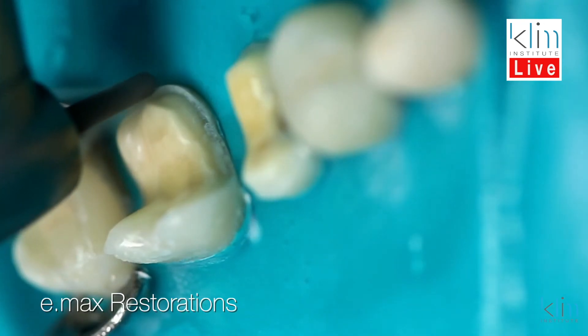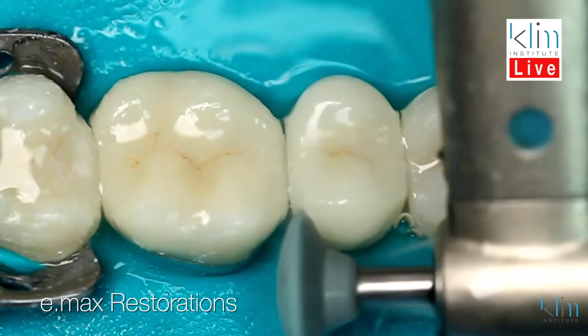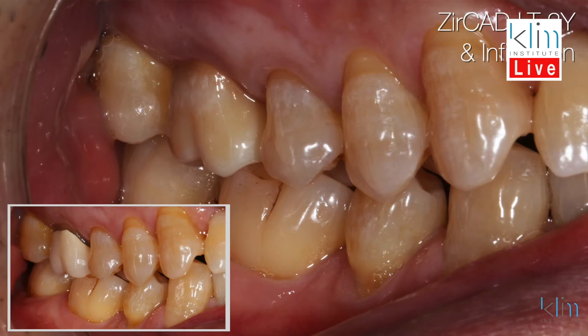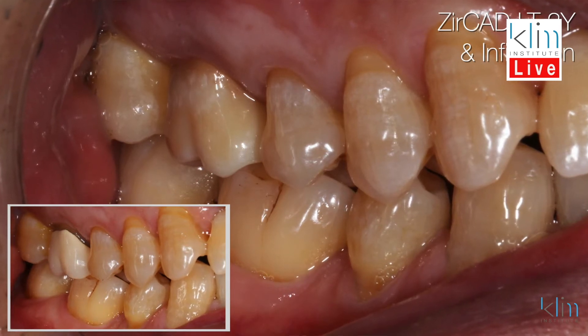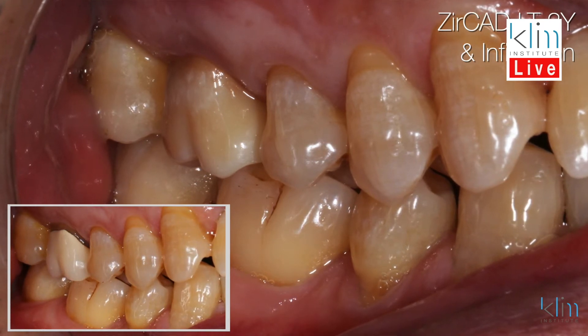I like lithium disilicate. I've used Emax for years — that is my go-to restorative material when I'm prepping onlays or more conservative preps, quite often posteriorly. If I don't have the room, I'm going to go to zirconia. We need to know the various brands and whether they are 3Y, 4Y, or 5Y strength factor, because it will dictate how you prepare. Fortunately, the manufacturer will provide their recommendation for prep style — pay attention to it, because the most important thing for the longevity of your restoration is occlusal reduction.